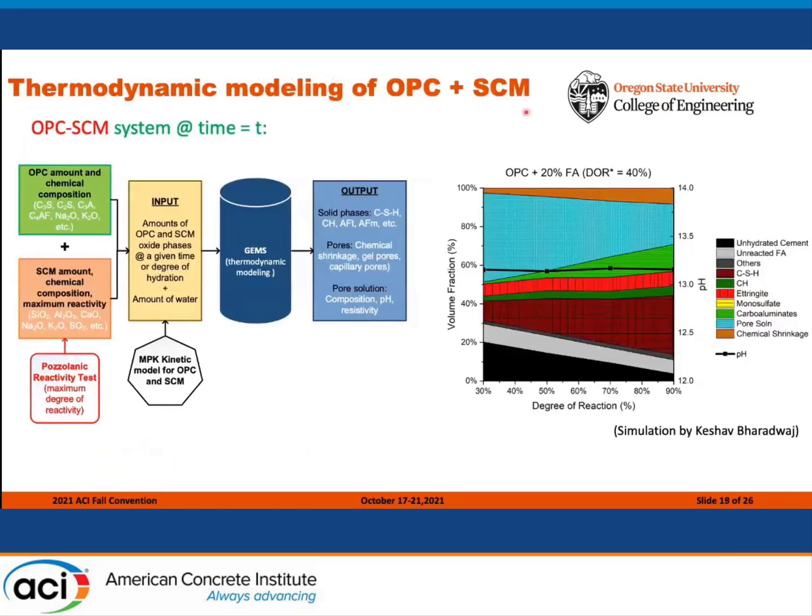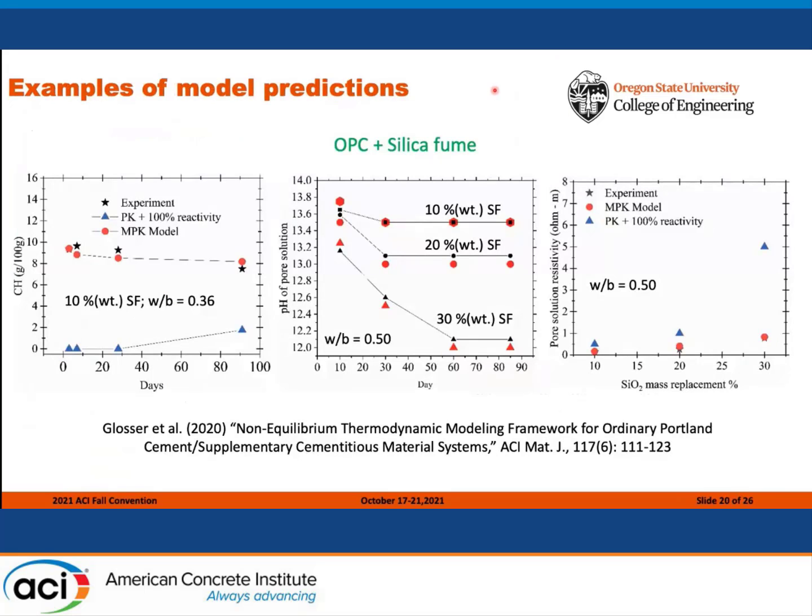to react. With the new modeling framework, including the Pozzolanic reactivity test and the MPK model, we can perform non-equilibrium thermodynamic modeling of systems containing SCMs. The figure on the right shows the volume fractions of input and output phases of such a simulation as a function of increasing degree of reaction. The benefits of this approach become clear when we compare the predictions with experimental data.